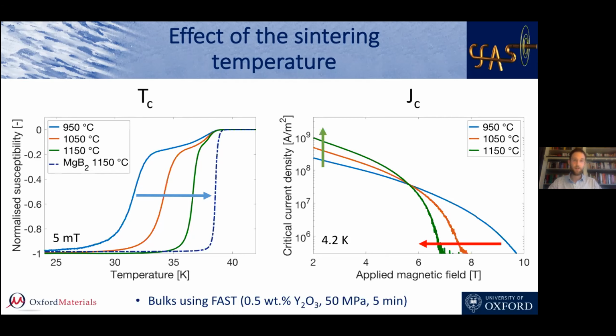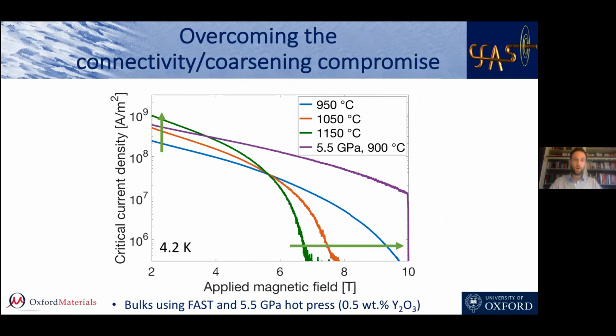So that's obviously quite annoying, but we went a bit further and we tried to overcome this compromise. And one way you can do that is to go back to the textbook and see: if I can't increase the temperature, what else could enhance my sintering? Well, pressure. Pressure is really good to enhance sintering, and so you don't have to go as high in temperature. So we had access to very nice cubic presses that are usually used to make diamonds. And so here in purple, we can see that by processing at the lowest temperature of the graph, so 900 degrees, not only do we improve the properties at low field, but we also hugely improve the properties at high field.